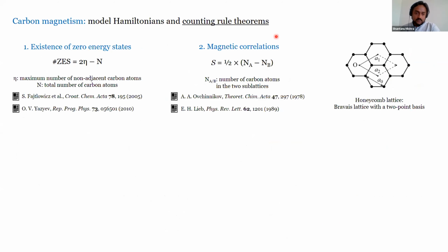And in principle, one may not need to do these calculations each and every time. A rather simple way of predicting these results is through these 2 counting rule theorems. The first is to predict whether or not zero energy states exist. And this is a result that comes from benzenoid graph theory, that the number of zero energy states should be twice the maximum number of non-adjacent carbon atoms minus the total number of carbon atoms.